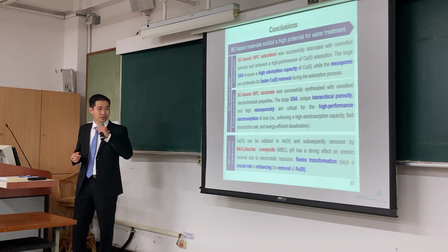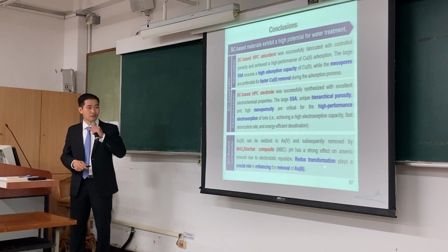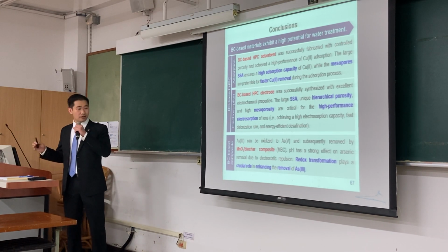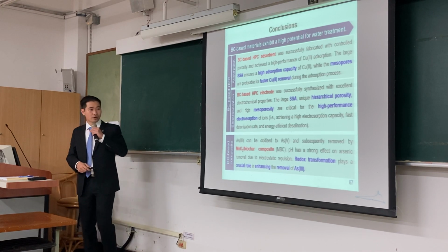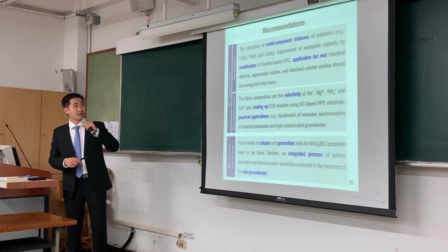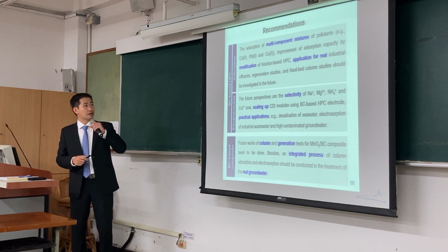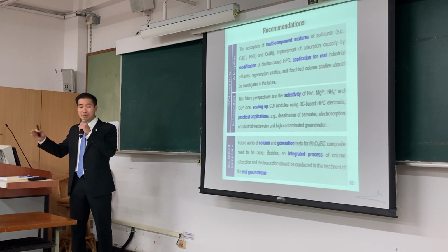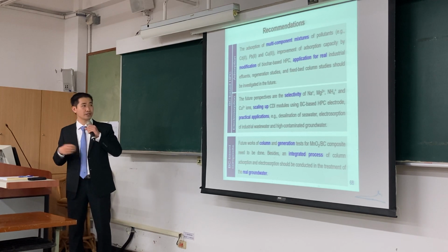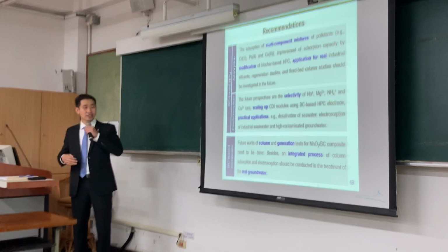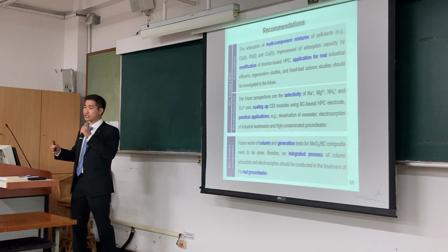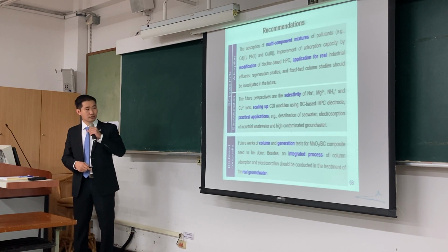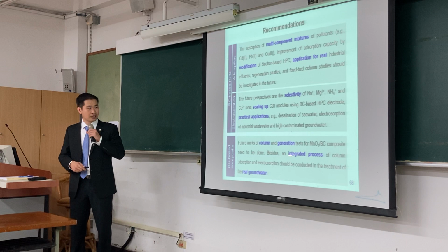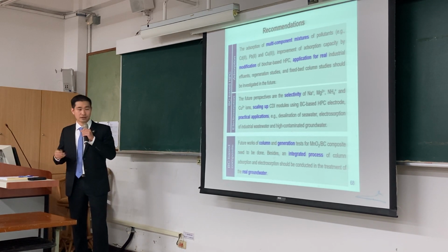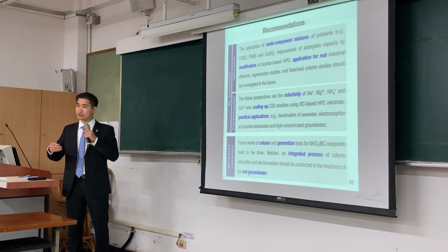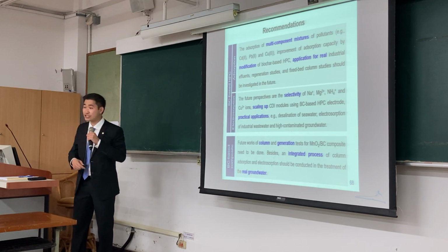Moreover, biochar-based composites show a high ability for redox transformation, and the redox transformation plays a crucial role in enhancing arsenic 3 removal. In my recommendation, in my first scope, multiple component mixing should be a modification of biochar-based HPC, and application at real scale should also be conducted. In my second scope, the selectivity of multiple ions, scaling up, and practical application should be conducted in the future. And in my third scope, the column regeneration experiment should be performed. Also, the integrated process between column and electroadsorption should be finished in the real water.